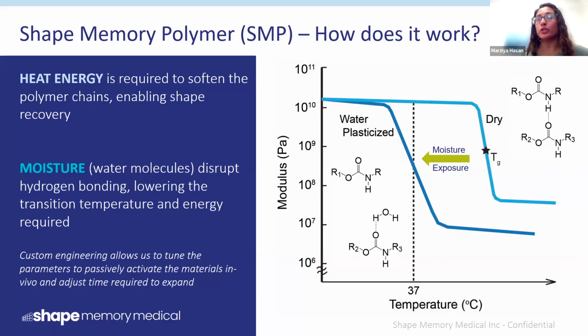But what ends up happening is that moisture from your aqueous body environment will make its way and penetrate the polyurethane network that we have created, and it'll disrupt the hydrogen bonding between the polyurethane functionalities. And that is what drives the Tg below body temperature. And once that Tg gets down below body temperature, it's pretty easy to trigger actuation, because now a 37°C environment is actually elevated heat, and that's what causes the foam to expand. So we're using both the heat stimulus and moisture plasticization to cause our devices to expand. And we have the capabilities to custom engineer our foams to be susceptible to moisture plasticization. We're able to move the Tg to very high, very low, sometimes even below 0°C. So these are all things that we can control in-house.